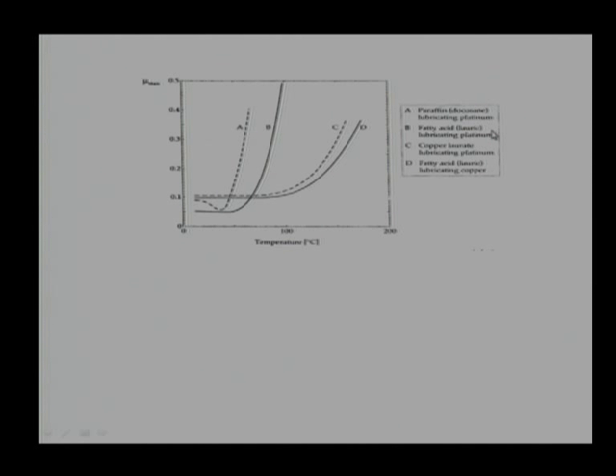However, if you use boundary additives or fatty acid as a boundary additive, then coefficient of friction increases only after a certain temperature, and that critical temperature is greater than the critical temperature for paraffin oil. When it reacts with copper, it makes a chemical layer. It is corroding the copper, making a boundary additive layer. Then this temperature increases substantially. From around 70 or 80 degrees, it may reach 140 or 150 degrees. Similarly, other oils can show different behavior.